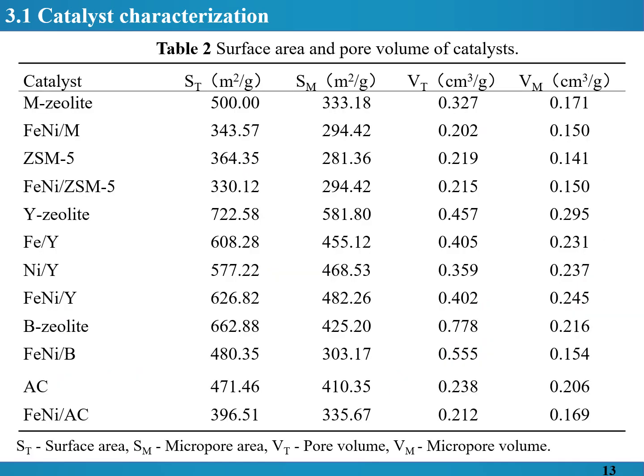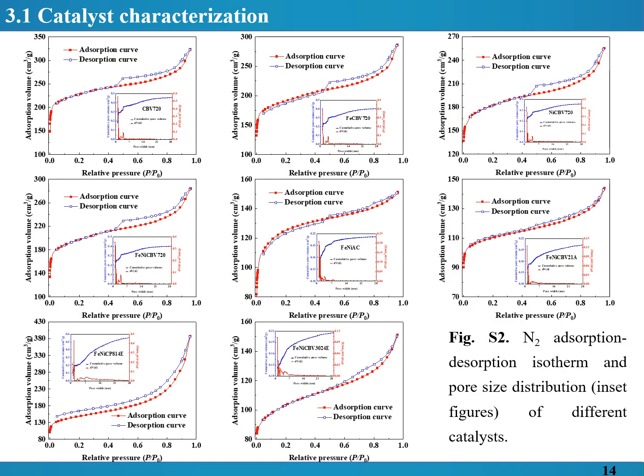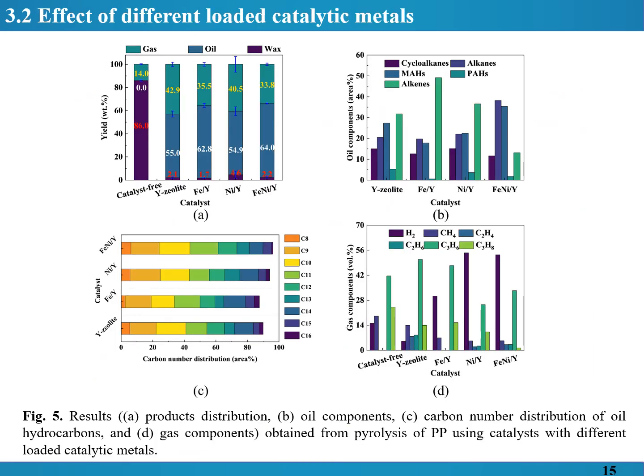Table 2 shows the surface area and the pore volume of catalysts. The doping of iron and nickel in zeolites and activated carbon led to a reduction in surface area and pore volume, mainly attributed to the pore blocking caused by the doping of iron and nickel. Figure S2 shows nitrogen adsorption-desorption isotherms and pore size distribution of different catalysts. Figure 5 shows the results obtained from pyrolysis of PP using catalysts with different loaded catalytic metals.